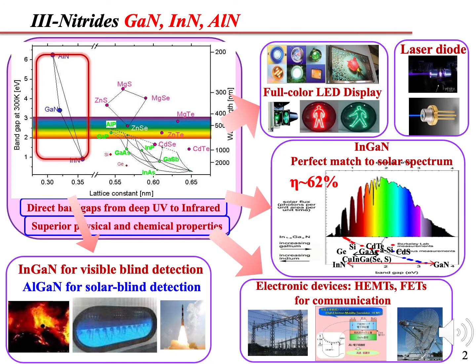The III-V nitride semiconductors include gallium nitride, indium nitride, aluminum nitride, and their quaternary and ternary alloys. They have very wide direct band gaps, from the deep UV region to the infrared region. For example, aluminum nitride has an energy band gap of 6.2 electron volts, and indium nitride has an energy band gap of 0.7 electron volts. So it almost covers the whole spectrum, which is much superior to other material systems.